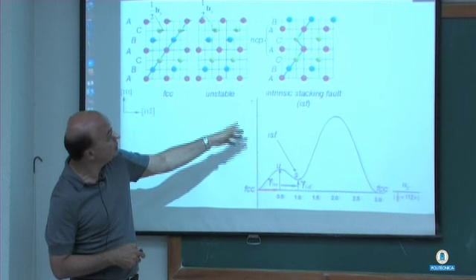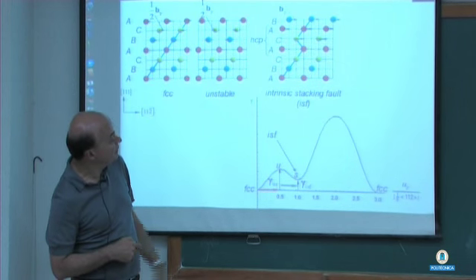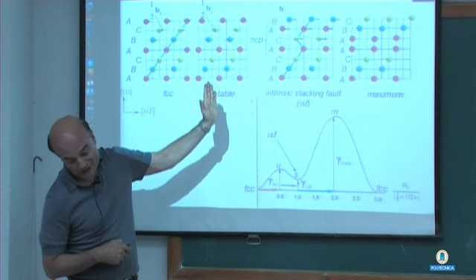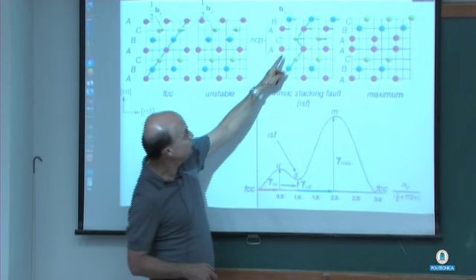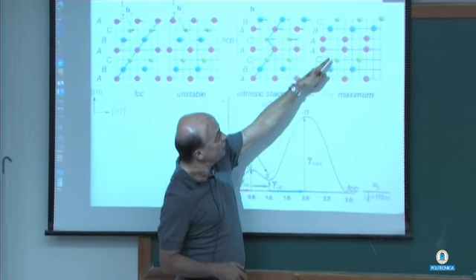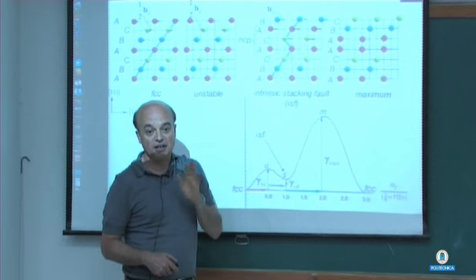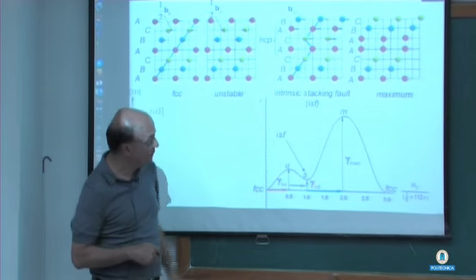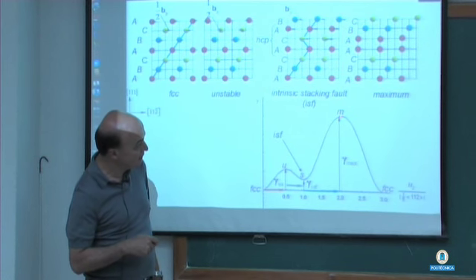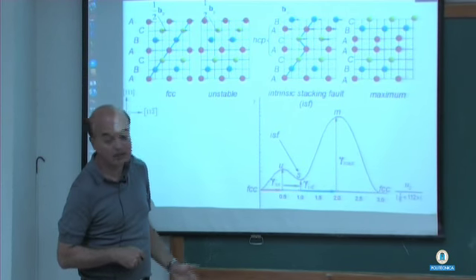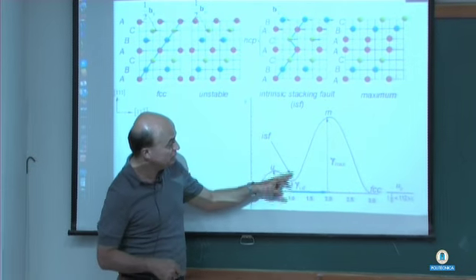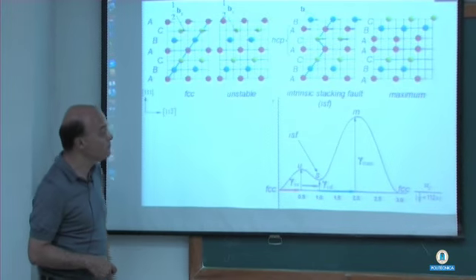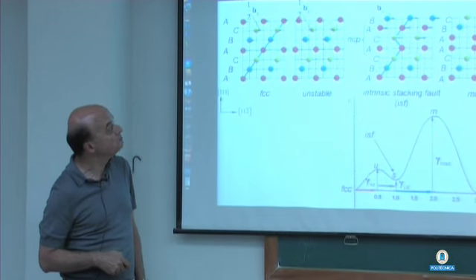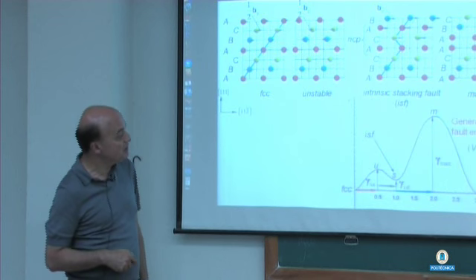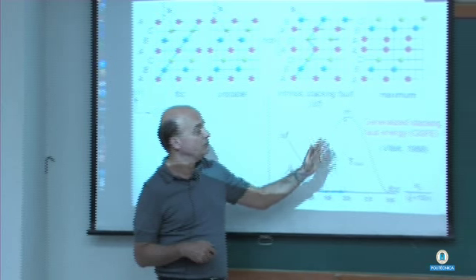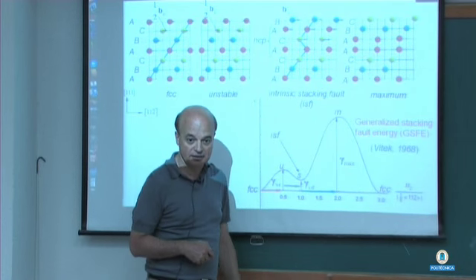Now, if you decide to move the atoms further, making atoms again move from left to right, then you get this AA stacking. That's a highly unfavorable situation. It will not happen because the energy barrier associated with that is very large, and that's called the gamma max. So you go here, but you wouldn't necessarily go through gamma max. Now this idea is called the generalized stacking fault energy, first introduced by Vitek in 1968.